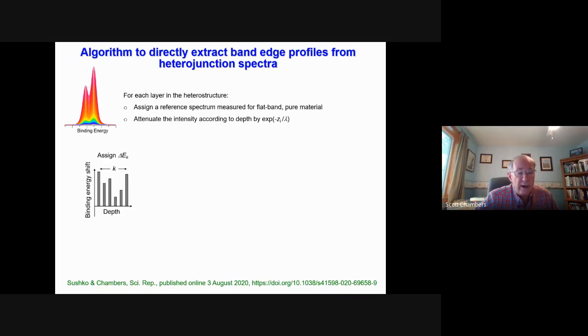We then use a random number generator to generate a random binding energy shift for each layer, and we assign those, and then we sort the binding energies from highest to lowest. In other words, we sort the distribution of binding energy shifts, so the binding energy is changing monotonically with depth, either one sign or the other, and we actually check both signs on the gradient of the potential. And the reason we do that is because we know that for a built-in potential, it's going to be a monotonic function of depth.